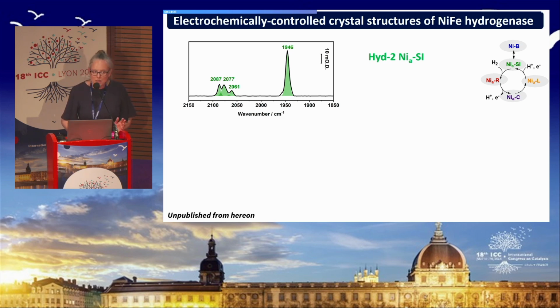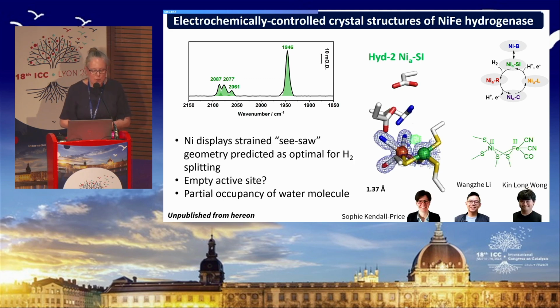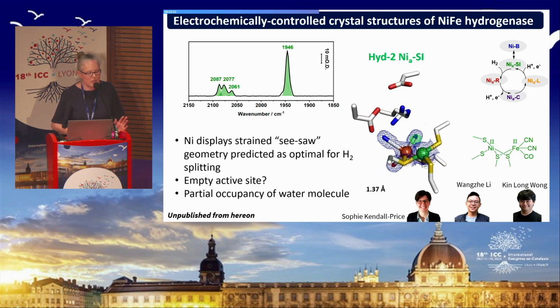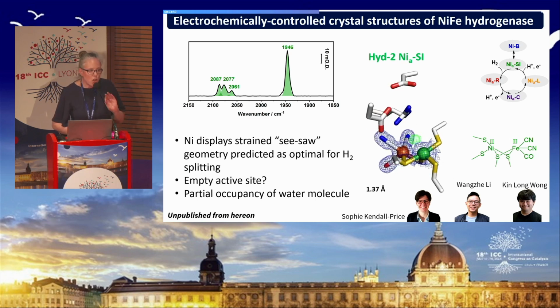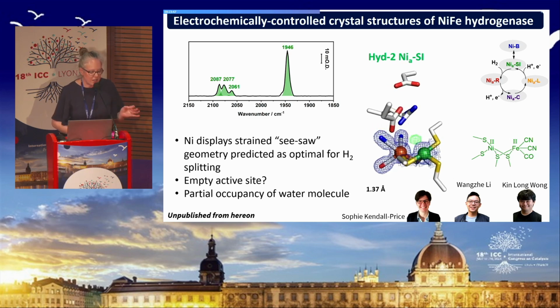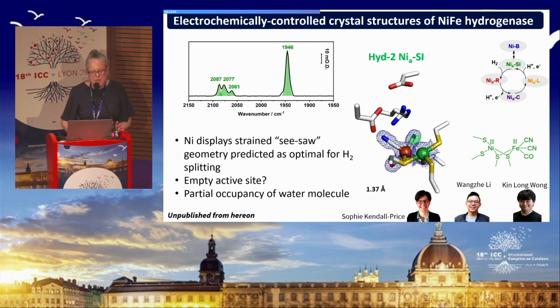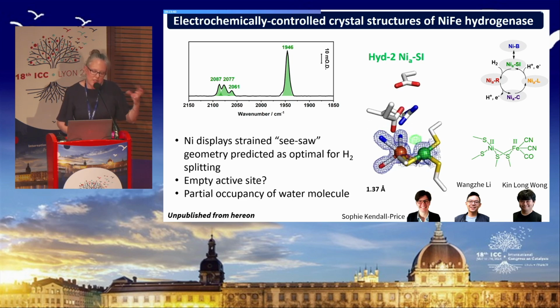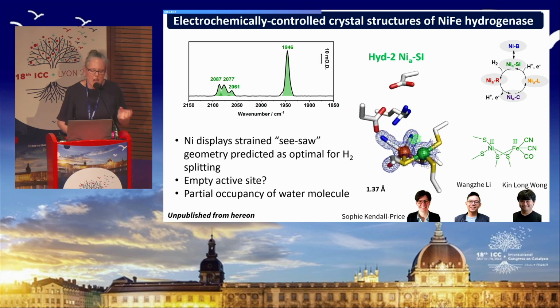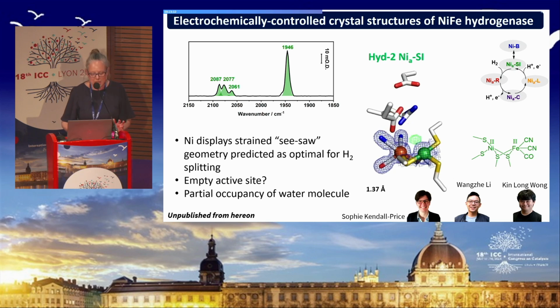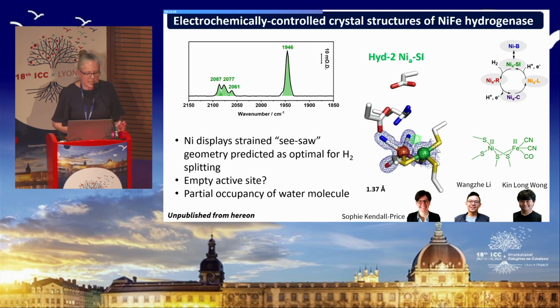We were unsure whether the crystals would maintain their diffraction quality after they'd been subject to electrochemical control. And so we were really delighted when we got a 1.37 angstrom resolution structure of this nickel Si state, where we'd lost no diffraction quality at all following the electrochemical control. The only other structures of this state that exist are one from photolysis of a CO inhibited form of the hydrogenase, or one from a very unusual hydrogenase where we know very little about the other states of that enzyme. So this was quite exciting to get this nickel Si structure.